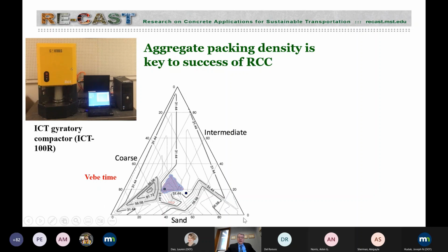And here we have a ternary diagram showing the sand, the coarse aggregate, and the intermediate grain size distribution between sand and coarse aggregate. The contour values are the values determined over here for the density. And we see that there are certain combinations where, sorry, this is the VB time, certain combinations where the VB time is reduced. So out there, the VB time, for example, is shown to be 30 seconds.